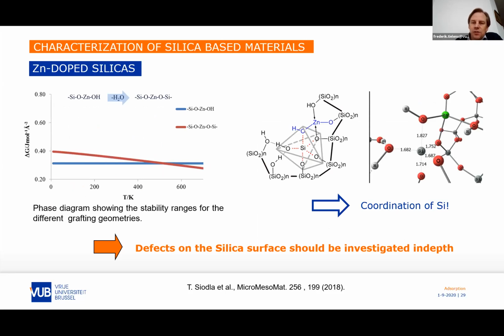But what for us was the most interesting part is that, in fact, the interaction distorts the structure in such a way that for a silicon next to the zinc, we obtain a pentacoordinated silicon, which is a very interesting defect in this structure, because defects are known to be important in reactivity. And we know also that in nature we sometimes have pentacoordinated silicon, but in structures which occur at high pressure. And here we found it by just grafting or putting a zinc oxide species next to a silicon in a special situation. So this opens the door to synthesizing materials with amorphous silica with specific defects, interesting for catalysis.